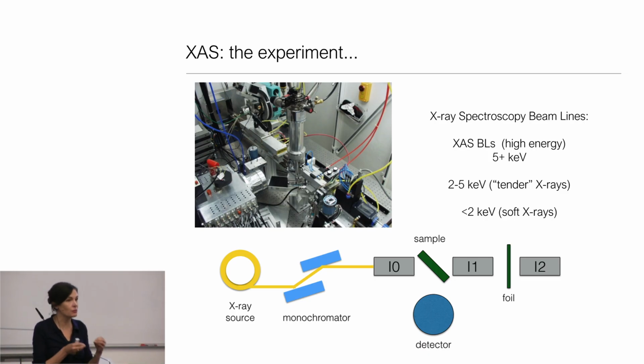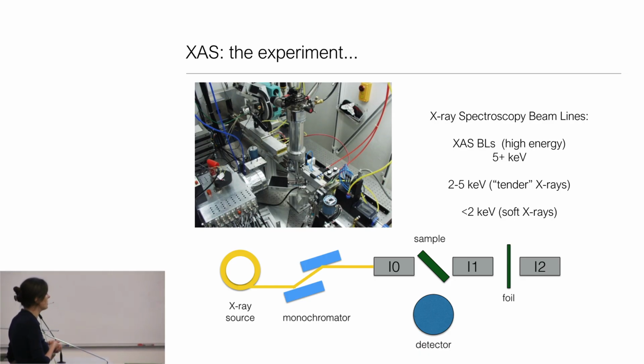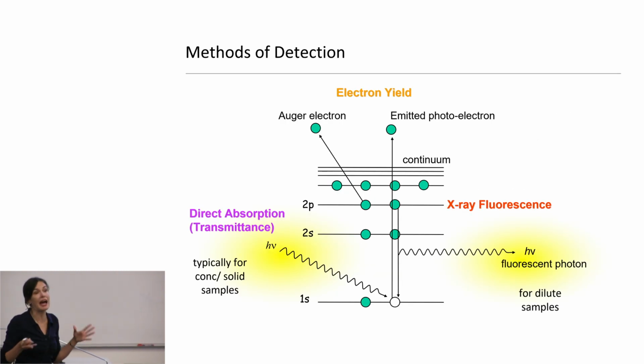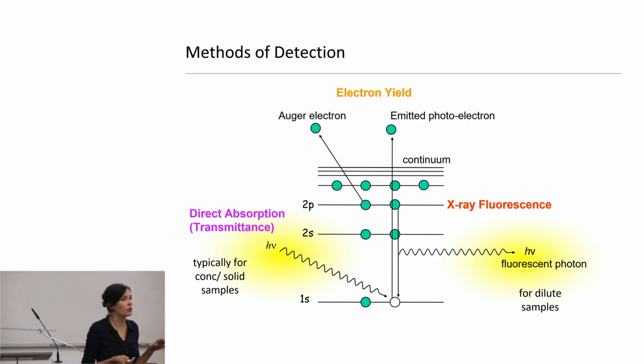It's not that often that we measure true transmission absorption. You can do that in a relatively concentrated limit, so 1% weight or higher, that's going to work just fine. For dilute samples, we normally are going to measure a secondary process. And so here it's helpful to talk about what secondary processes are actually happening in my sample. And of course, once I create this core hole, the system can relax in various ways. And a pretty high probability exists that you could actually have an Auger or electron yield decay where you actually eject a photoelectron. This has relatively high probability, especially at low energies, but typically, if you don't have to follow an ejected photoelectron, you don't want to because it has a very short path.